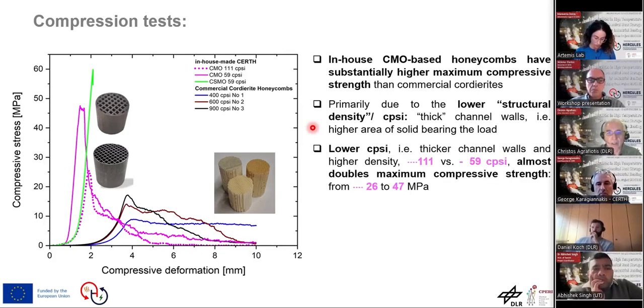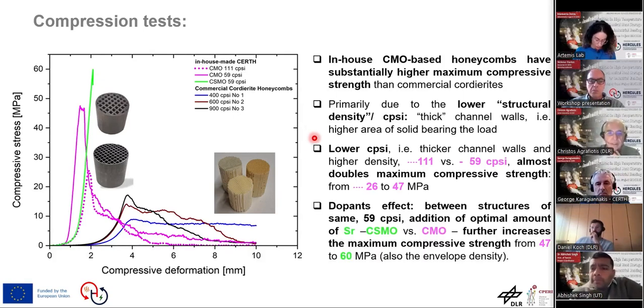And if we click once or twice more, we can see also that the effect of composition and the walls have an effect. Structures of the same compositions but with thicker walls, less CPSI, have a higher strength, as you see in the magenta curves, whereas a proper dopant can improve further the mechanical strength for the same compositions, and that's how we get the green curve there.